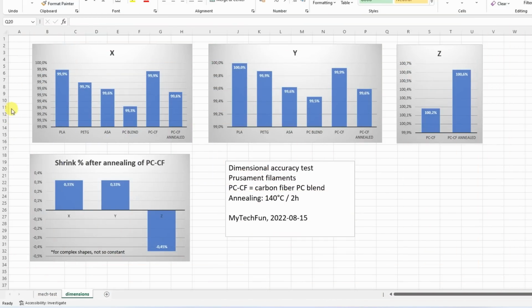And this is a summary of the measuring, and here you can see the values in percentage, the difference from the nominal perfect value. So 100% is the perfect dimension. And with the four basic materials, something I expected: the shrinking of the PLA is the smallest, so it is the most accurate. Then the PETG, ASA, and the biggest shrinking I had with the PC blend.